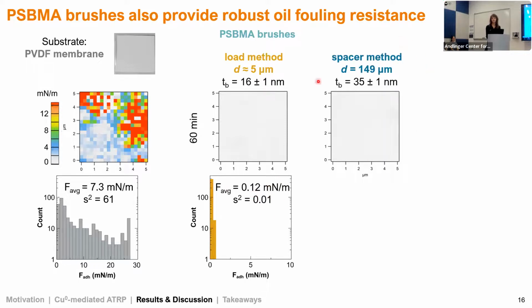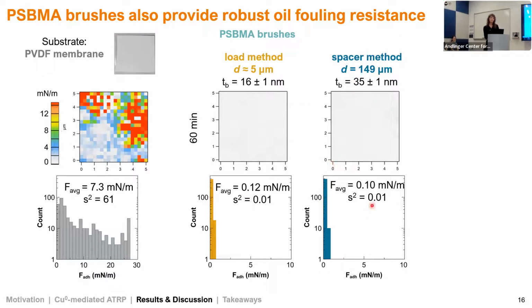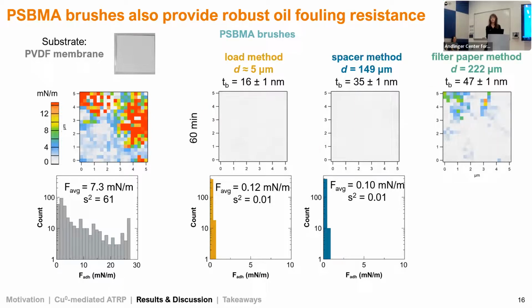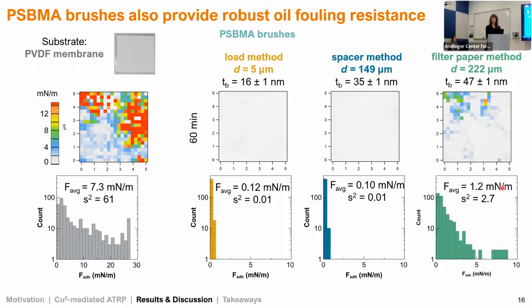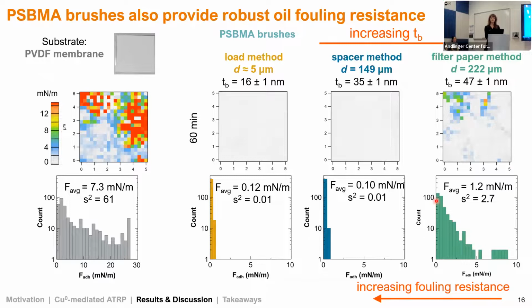When we go to the spacer method, increasing brush thickness, we don't see much of a difference visually. But looking at the histogram, we've slightly improved the average adhesion force with similar variance. So these are pretty similar, but performance is good. But then when we go to the filter paper method, even at higher brush thickness, yet again we're seeing lower fouling resistance. The average adhesion force here is an order of magnitude higher than for both the spacer and load methods, with a much higher variance. So yet again, increasing brush thickness, fouling resistance is actually going the opposite way.